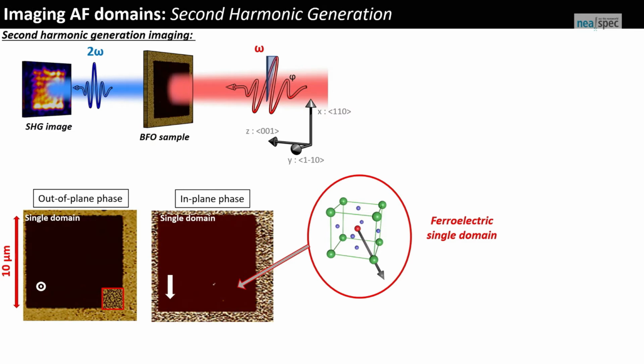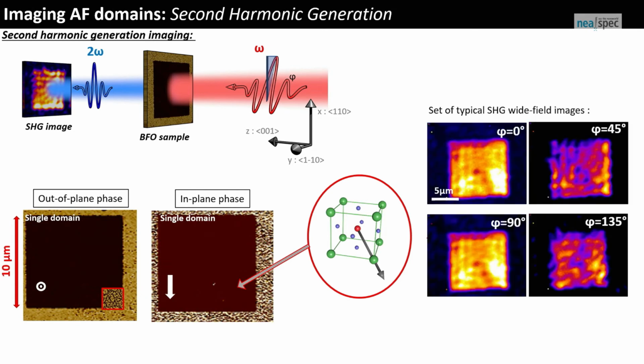trick we used: we decided the samples are definitely too small, so we decided to write with the PFM tip, applying a voltage on the PFM tip, large single ferroelectric domains, 10 by 10 microns. We built a transmission microscope, where it collects this light in a wide-field manner, and these are the typical images you can get for different orientations of the polarization.